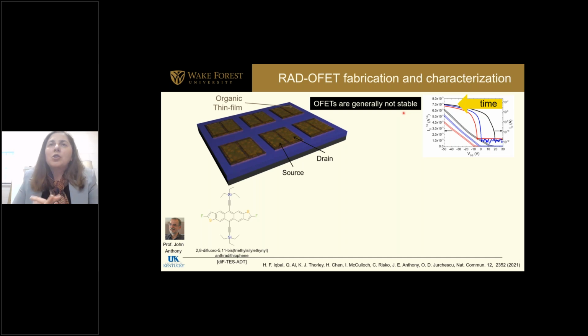The problem is that in general, organic transistors are not very stable. So this means that in time, either because of exposure to environment or because of bias stress, the current voltage characteristics will shift. Here in black, you see the time zero current voltage. And then after certain stressors, you see this huge change. So then it will be very difficult to understand how much of this change comes because of the exposure to radiation as opposed to environmental or bias stress effects.